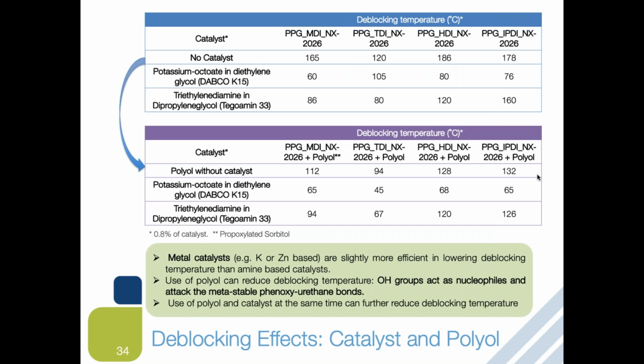So this is a busy slide, but when you look at the slide, so here what we have done is we basically prepared PPG-based pre-polymer, functionalized with the 4 different isocyanates, so MDI, TDI, HDI, IPDI, and then those prepared pre-polymers are blocked with NX 2026 in this case. And then we measured the deblocking temperature using DSC analysis method. So here, without anything else, we measured the deblocking temperature of the pure system, and you can see typical deblocking temperatures are pretty high. 120 being lowest, but it can require 186 degrees to deblock.